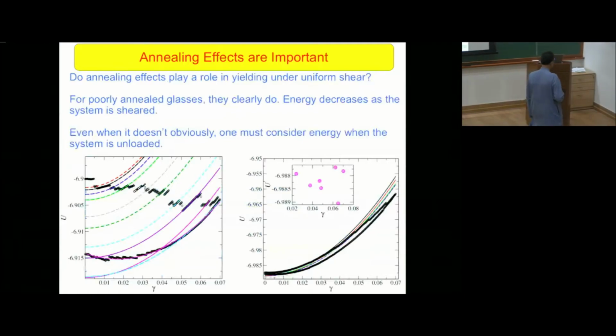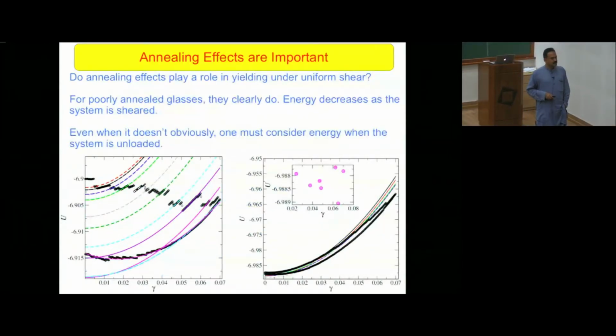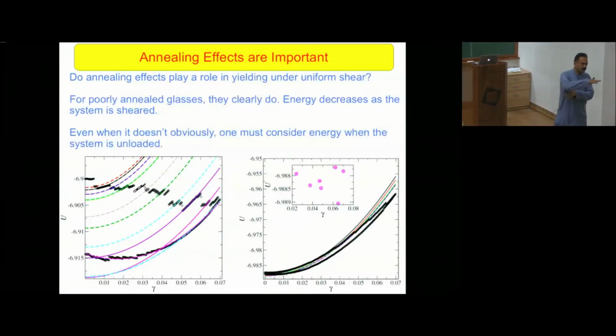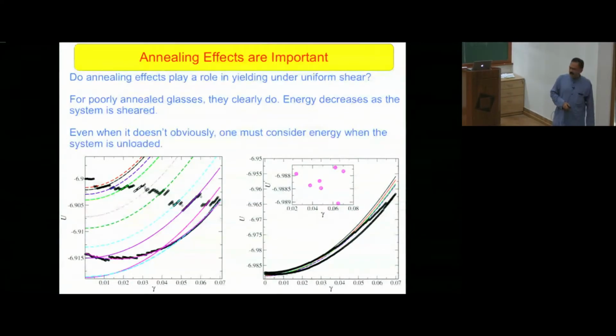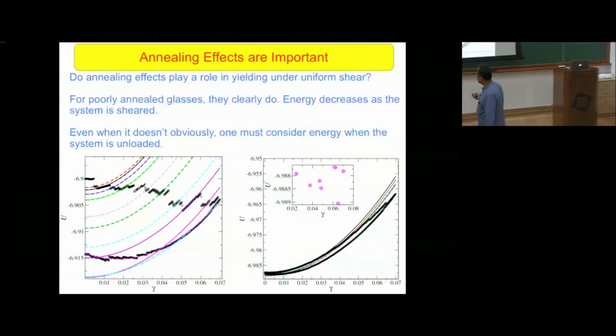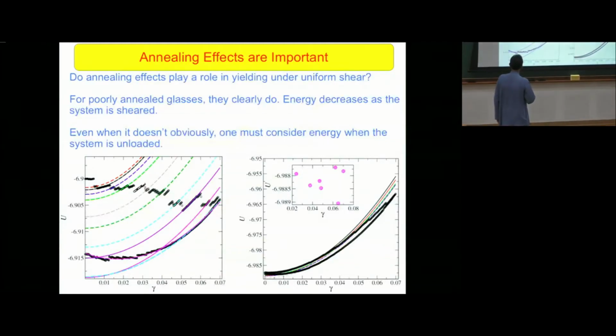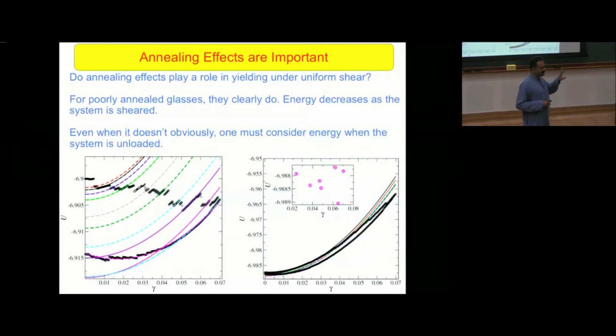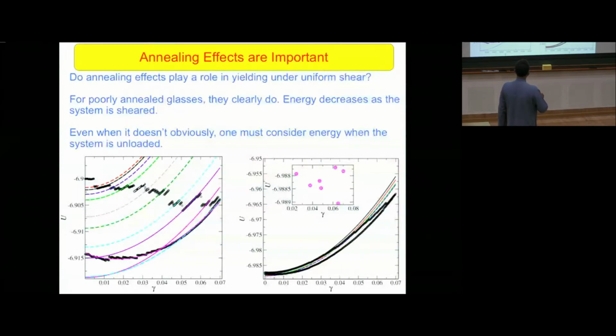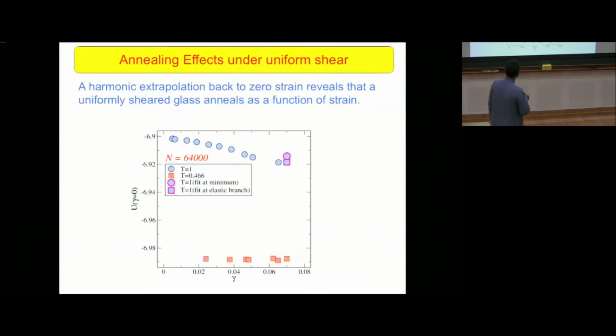that will add to the understanding of this. But in the meantime, you can ask, okay, maybe annealing is important when you do this cyclic deformation, but why should I care if all I'm interested in is driving the system towards yielding by just a uniform deformation? And the answer is shown here. This is now the poorly annealed glass, and this is what happens to the energy as I shear it forward, right? If you just focus on this curve, you see that this system, even under uniform shear, clearly is annealing, going to lower and lower energies. But you can also try to factor in what I said earlier, which is that the energies that I'm seeing here are the energy of the unstrained system plus elastic energy, right? So I can make an effort to project back to zero strain and look at those energies, and that's what you see here.